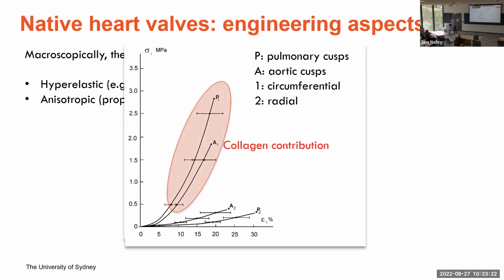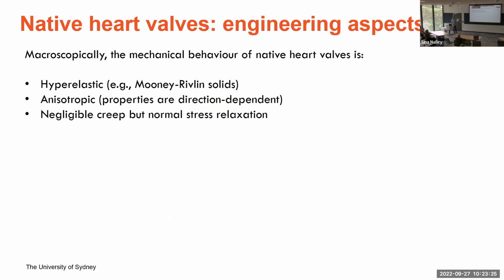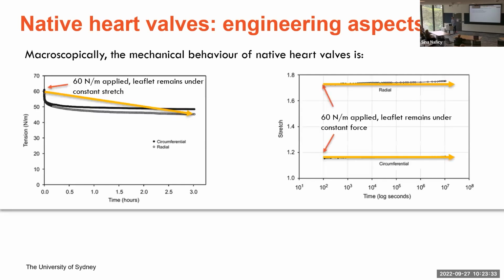At the same time, we would see that these leaflets have very negligible creep, but they relax under stress. What it means is that if you apply a stress on a leaflet, they tend to restructure internally and release some of this stress. So they dissipate energy.